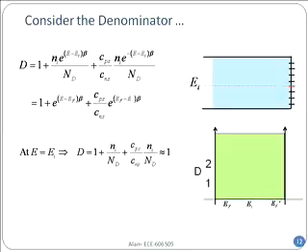So let's try to evaluate that denominator at energy level E equals EI. Now when energy is E equals EI, from the previous expression, you can see that the second term will become Ni divided by Nd. Ni is 10 to the power 10, Nd is 10 to the power 18. So that number is gone. And the other term similarly is Ni over Nd. That term is also gone at the intrinsic level only. So the magnitude of the denominator at the intrinsic level is 1, essentially 1.